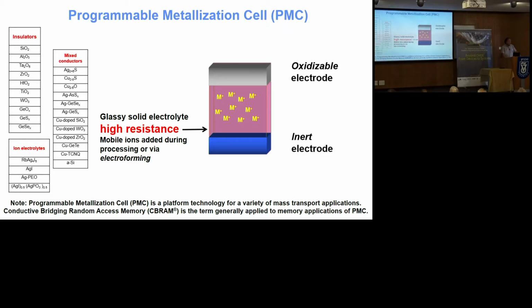The electrodes are, in our particular case, in these cation memories, we saw a great talk from the gentleman from HP earlier on talking about oxide-based, anion-based devices. We were cation. And in that case, we do need some form of oxidizable electrode that can supply ions into the reaction environment, and an inert electrode that basically just provides electrons for the reduction of those ions. And those electrodes can be typically on the oxidizable side, silver or copper, and on the inert side, it can be anything that basically can conduct but not react electrochemically with the system. So tungsten, platinum, that kind of stuff works fine there.